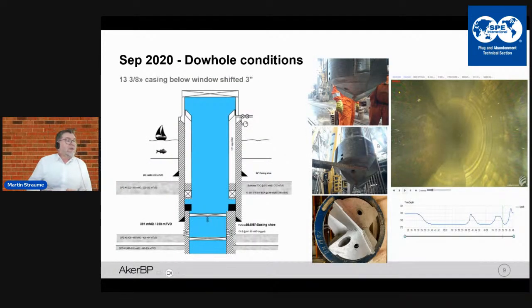So during this 2-year period, we filmed it downhole and on surface, and we didn't see any bubbles coming to surface. So what we did was that we designed a mill to mill out the bismuth plug.